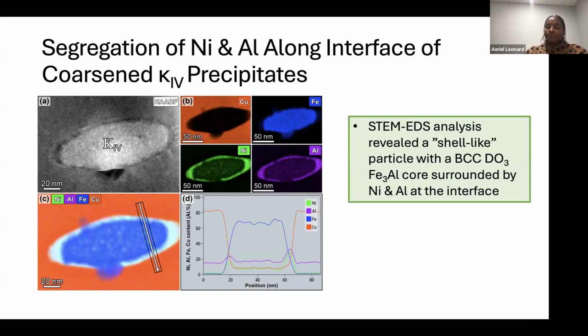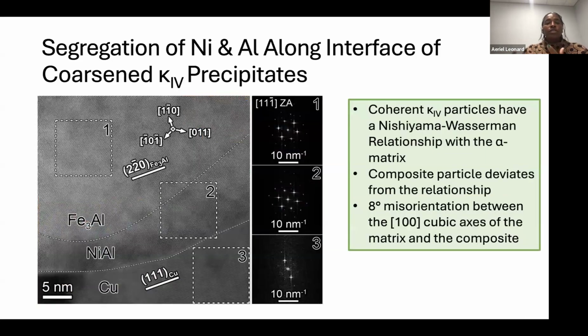When we took a closer look, in general, coherent kappa 4s have the Nishiyama-Wasserman relationship with the alpha matrix. What we learned with this shell-like composite particle was that it created an 8-degree misorientation between the cubic axes of the matrix and the composite. So it deviated from this Nishiyama-Wasserman relationship. And through some of the more characterization that we did, we learned that this did hinder dislocation motion. Now, does it have a large effect on hardening? Not so much. It's very few of them, and there are really only a few of them at each boundary as you go along.